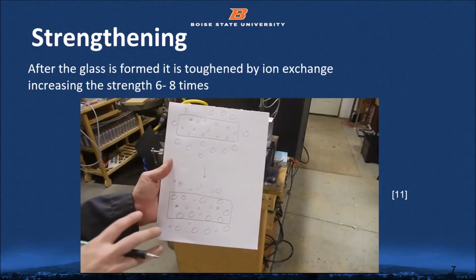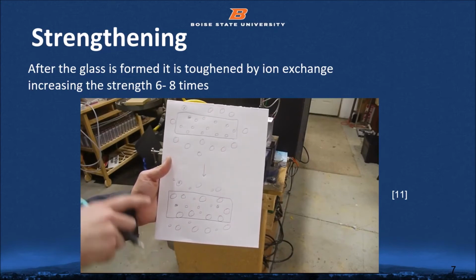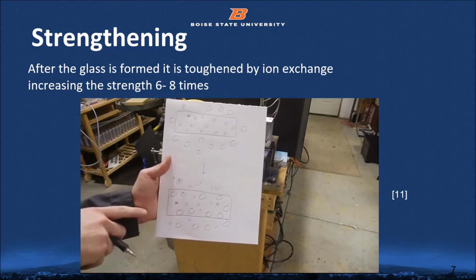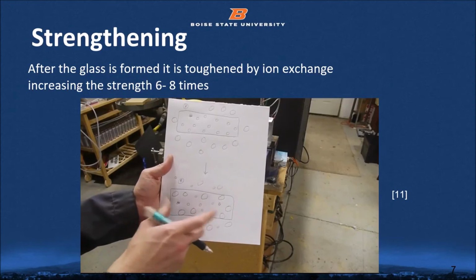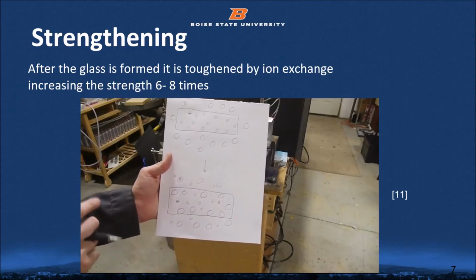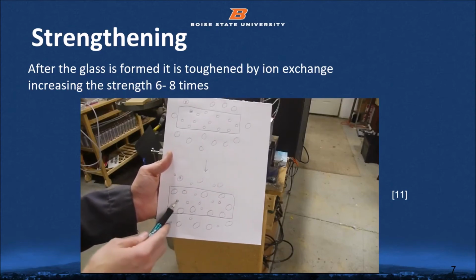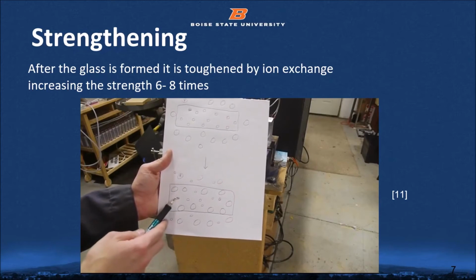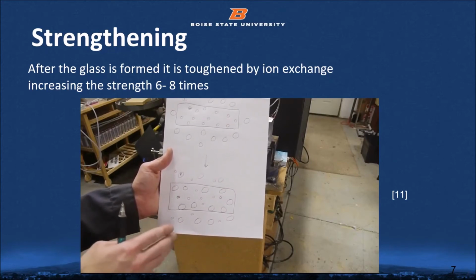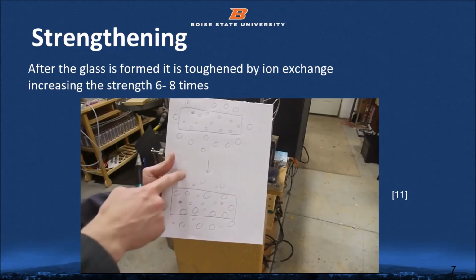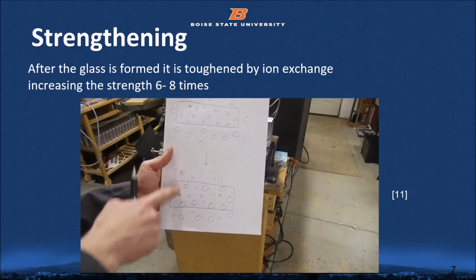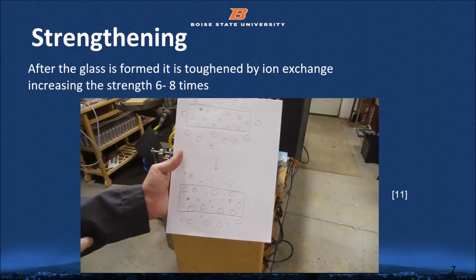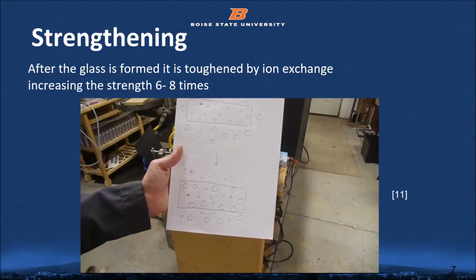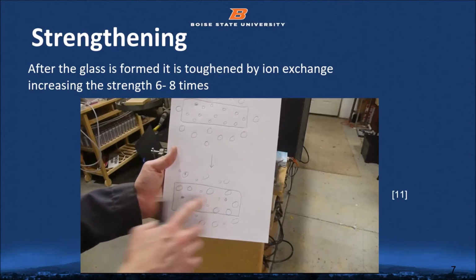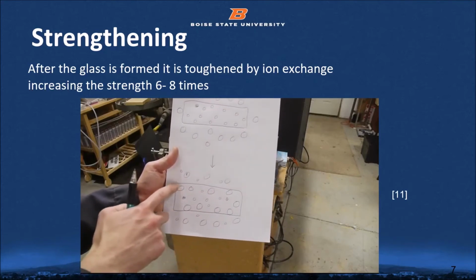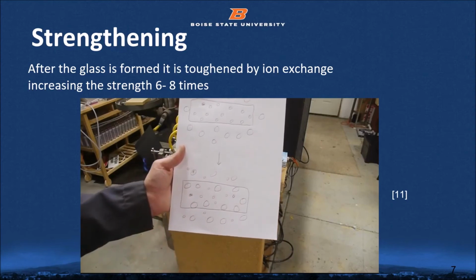So the glass is still hard when this is happening, and as we're shoving in these larger atoms, the glass is becoming increasingly put into compression. However, the center of the glass is not affected by this process as quickly, because this is like a diffusion process, and so it takes a while for these potassium atoms to work their way into the glass. So if we cancel the process after a certain amount of time, the center of the glass will not have this effect at all, and the edges will be in compression.